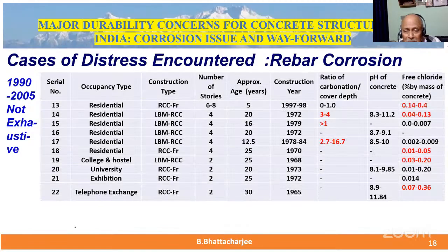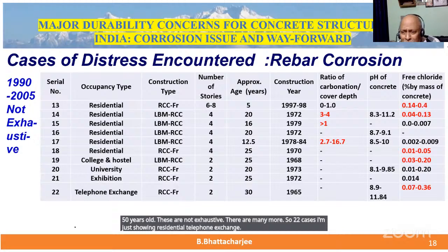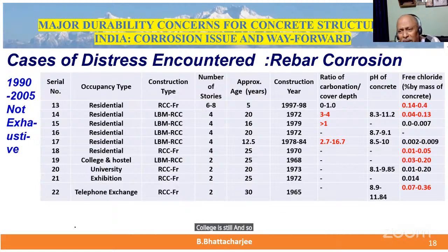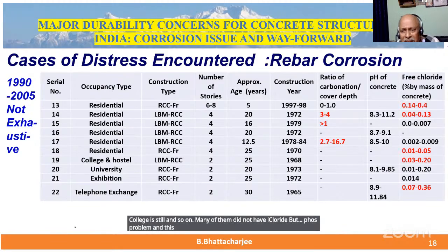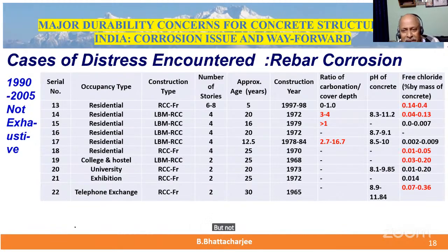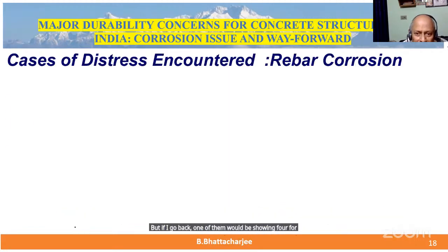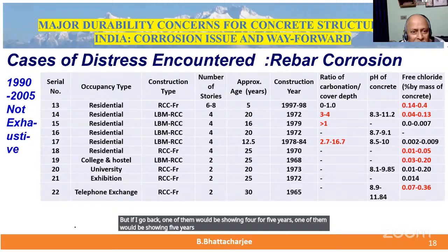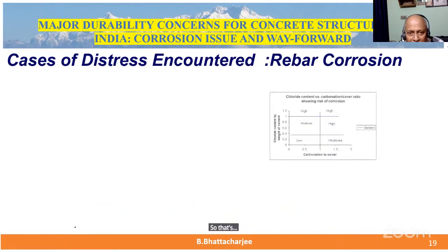These are not exhaustive, there are many more. So 22 cases I am just showing: residential, telephone exchange, college hostel, and so on. Many of them did not have high chloride, but pH was a problem. And some showed 20 years, but not 4 or 5 years, right? But if I go back, one of them would be showing 5 years of life. That is the first one, this one, and it actually had quite a bit of chloride in it. So that's one.